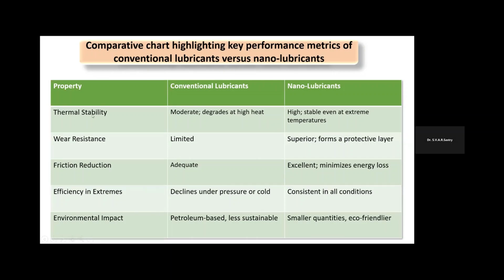So in terms of properties, first property, thermal stability. The conventional lubricants are moderate in thermal stability and they degrade at higher temperatures, whereas nanolubricants have high thermal stability and they are stable even at extreme temperatures. The wear resistance is limited for conventional lubricants, whereas for nanolubricants it is superior. Then the friction reduction is adequate in conventional lubricants, whereas in nanolubricants it is excellent and it also minimizes the energy loss. In extreme conditions, efficiency declines for the conventional lubricants, whereas for the nanolubricants, the efficiency is consistent in all the conditions. And the last one is environmental impact.